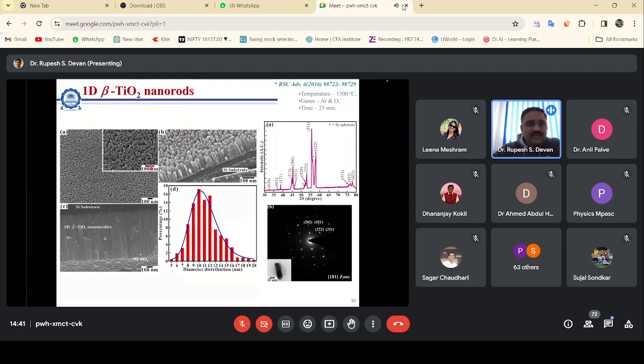So here, when we synthesized, in the top view you can see this looks like particles on the surface, but these are actually vertically grown one-dimensional structures giving a thin film of approximately 600 nanometer. And the dimensions of these rods are less than 30 nanometer. It's between 5 to 20 nanometer. Now, here, the maximum rod dimensions were close to 10 to 11 nanometer. Here you could say that this is probably the anatase phase. But the X-ray diffraction and TEM analysis show the brookite phase. Now, the question here is why we observed this brookite phase.